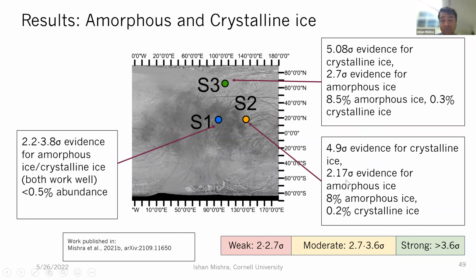Not so much for amorphous ice, which was detected at lower significance. And what we think is happening here is that the reason S2 and S3 are showing very strong evidence for crystalline ice, whereas S1 is not, is probably because S2 and S3 are coming from regions that are further away from the irradiation-dominated regions. And so that means that the water ice has not been amorphized to greater depths. Because reflectance spectroscopy is probing the very top layers, probably those regions are still crystalline and it's not being converted to amorphous ice completely. So even though the crystalline ice abundance we're getting is very low, there is still a strong detection.